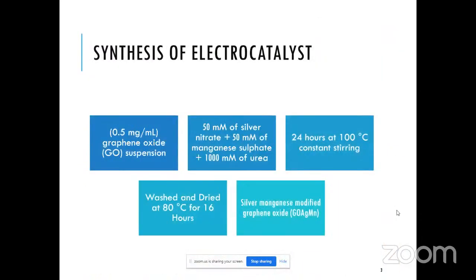For this purpose, I have synthesized an electrocatalyst with graphene oxide, silver, and manganese. To the graphene oxide suspension, I added silver nitrate, manganese sulfate, and urea and allowed it to react for 24 hours at 100 degrees Celsius. After that, they were purified and dried to get the silver manganese modified graphene oxide electrocatalyst. This scalable urea hydrolysis method of synthesis will help in mass production of the electrocatalyst, which may be further helpful in commercial application of this sensor.